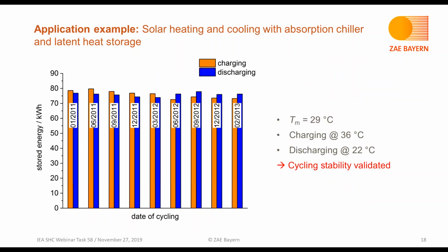With this system, it has been in operation for several years. And here you see the results of the thermal cycling at storage level, again applying a charging temperature of 36 and a discharging temperature of 22 degrees C. And thereby we could validate the thermal cycling stability for this material in this storage configuration.